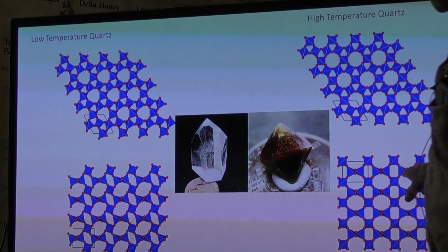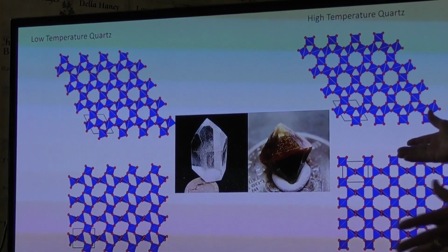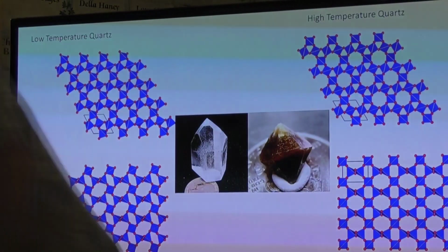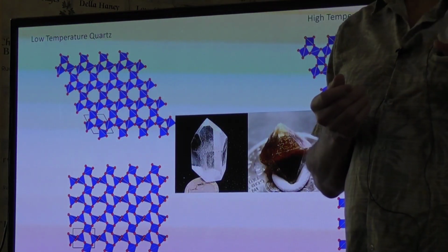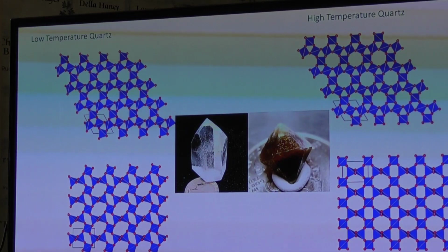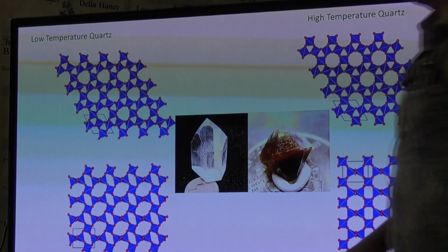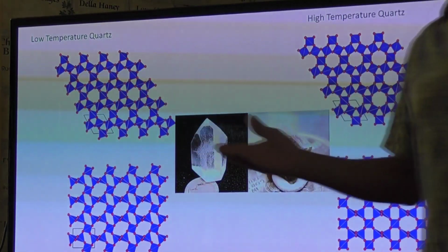And you can see in the quartz structure there's holes, all right? And the holes will be filled with other stuff. This clear quartz right here is probably only 99% quartz, maybe less than that. It's 1% other stuff. So people who make silicon for products are going to add things to it, and they don't want other stuff that they didn't add in there. So they look around for quartz where the holes aren't filled with stuff, that's pure. There's an example of that in North Carolina somewhere. It's special quartz, it's extra clean.